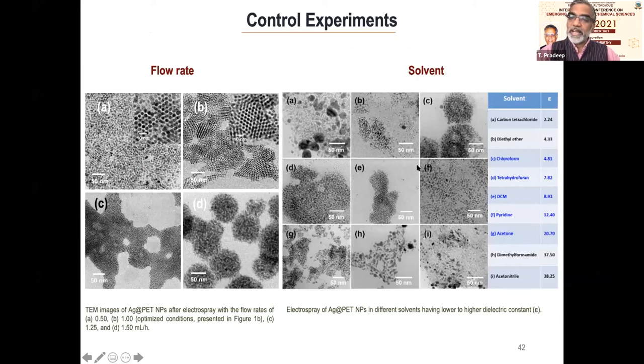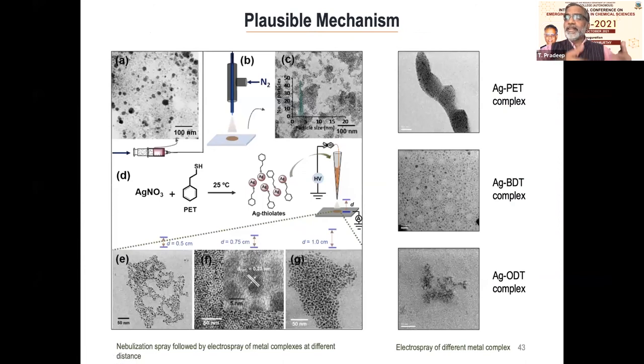So essentially what happens is that these particles are protected with thiols. So what you have are metal thiolates on the surface. Now, you think that these particles are decomposing to thiolates, and then thiolates are reassembling to give you metal particles. So in order to test this hypothesis that particles are becoming thiolates, we make thiolates and then ask the question whether they form particles. And we also spray. And at a particular distance, you also collect the material and show that there are thiolates being formed in the solute during spray.